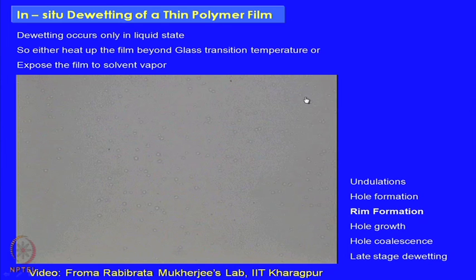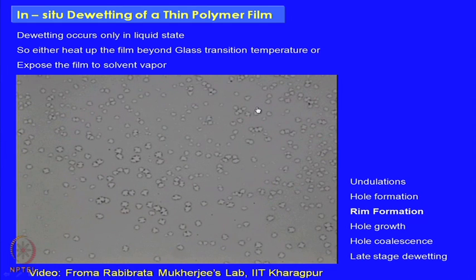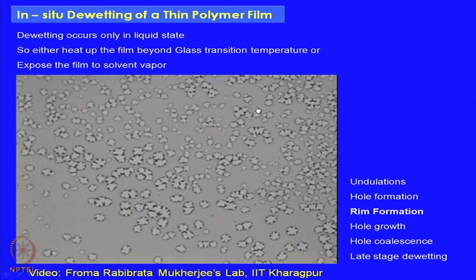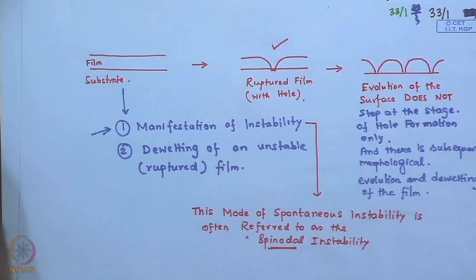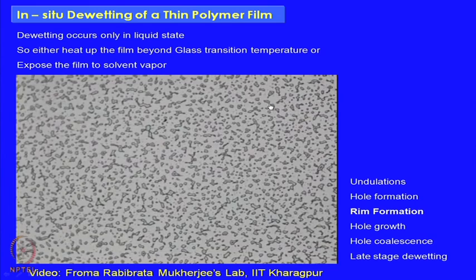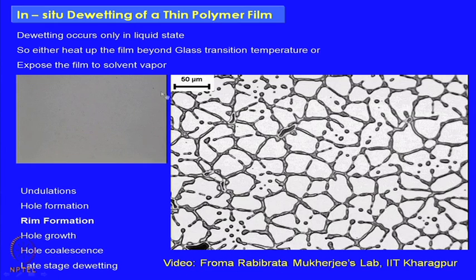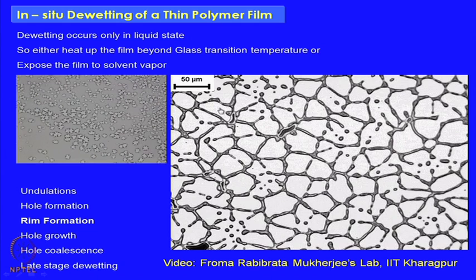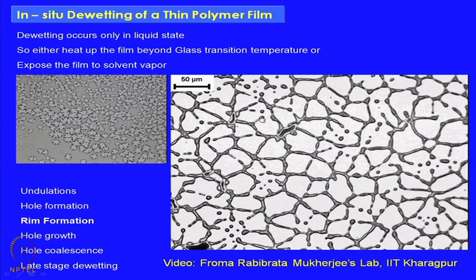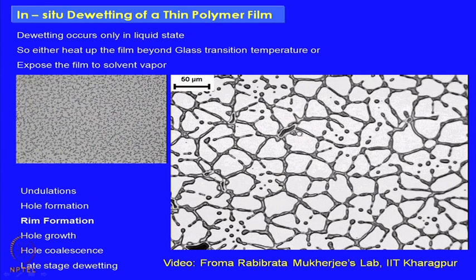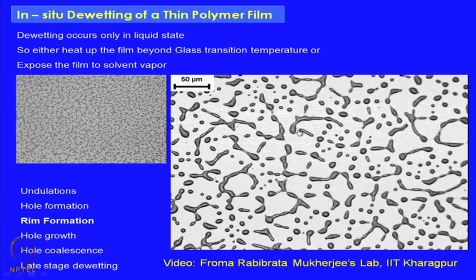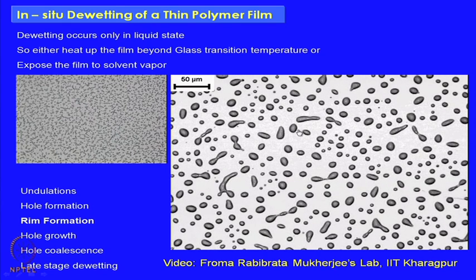What you are seeing now on the computer screen is a scenario where the film has just ruptured and the holes have just started to appear. Once you heat it further, you see the holes are growing, and there is some additional dynamics occurring. These holes grow, and eventually result in some isolated droplets. This is the video you just saw, in a smaller size now. You have these holes appearing, then the holes grow, and eventually at the late stage they form isolated drops. You can see at a higher magnification what happens at the late stage. You see some polymer ribbon-like structures, and then these ribbons become unstable and break down, forming random isolated polymer drops.